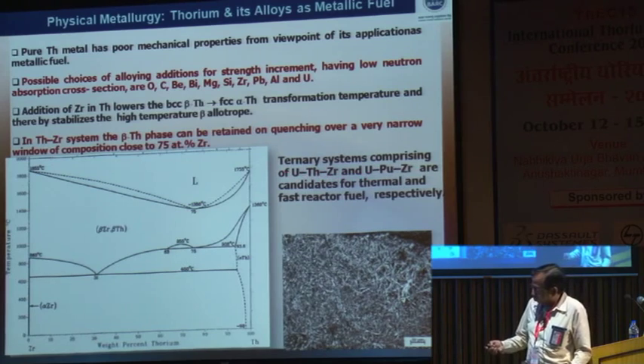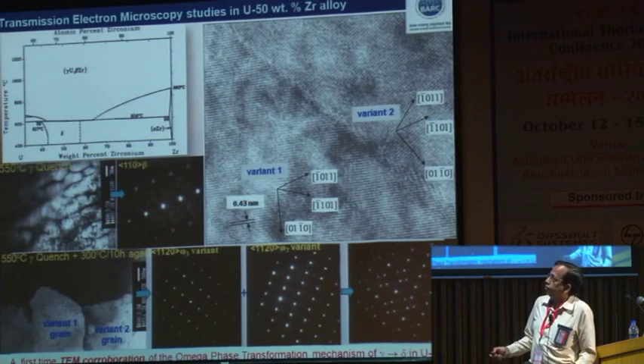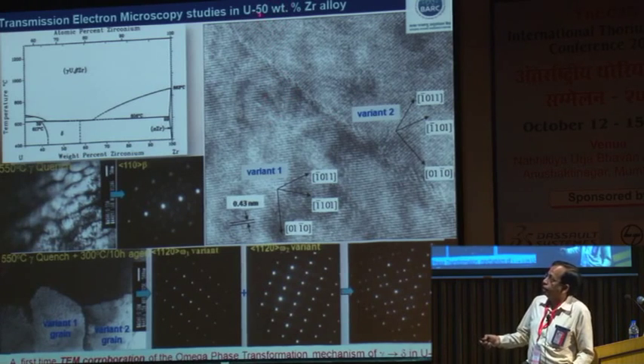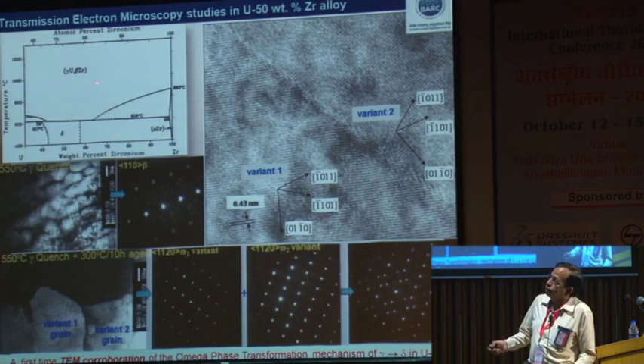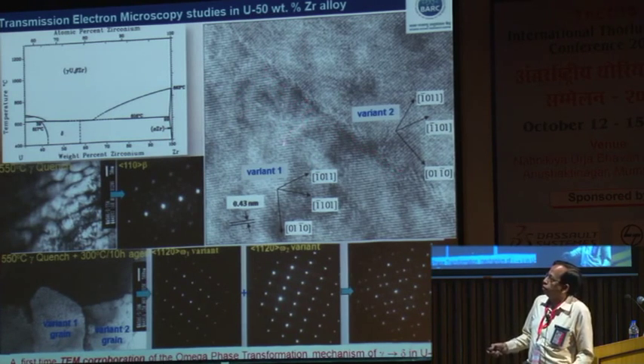And the next slide shows a glimpse of the physical metallurgy or the transformation aspects in the uranium 50 weight percent zirconium alloy, where you can retain the beta phase, and on aging it transforms to the omega phase. So this is one of the first few examples of omega phase seen in uranium-based alloys, and this is the high resolution image done in BARC showing the two different variants of the omega phase in this particular alloy.